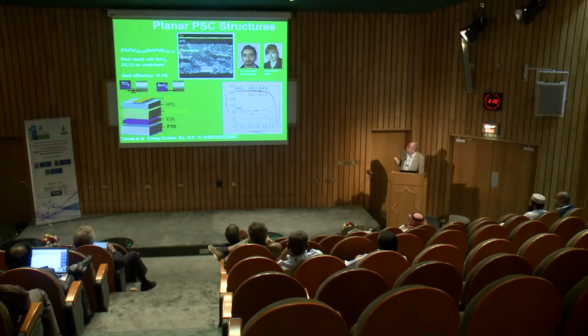The reason we think TiO2 does not work with this ALD deposition is that the conduction band of TiO2 is too high compared to the perovskite, so we cannot inject into the TiO2, whereas tin oxide seems to be ideally matched with ALD to the perovskite and gives high voltage. This is what we can explain it with, but there could of course be further explanation, and we have a collaboration with Professor Bisquert here who seems to have some interesting data on that topic. So there is more to be explored here.